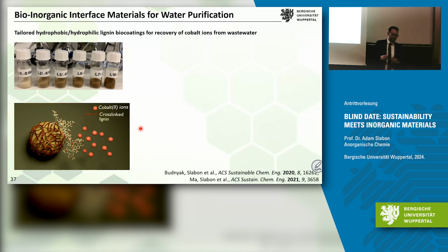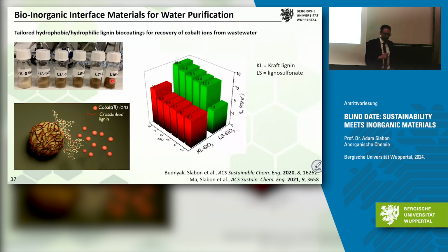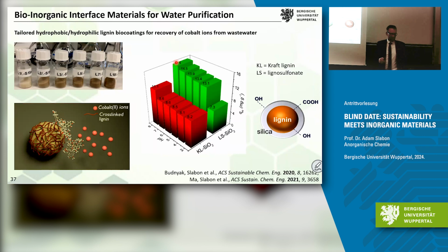Then you can take these adsorbed powders to another solution, change their pH, and recover them at room temperature. It works quite nicely for these composites. Here's the uptake of cobalt which we can get from wastewater, because you have the functional groups where the metal ions can adsorb.